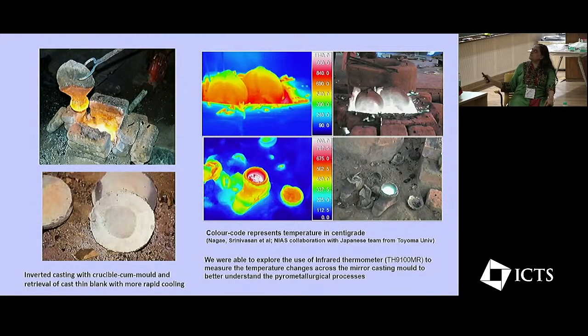We also use various other techniques. This is a thermal camera here, which is quite useful to understand what is happening in terms of the temperatures in the foundries. You can see the color coding here. What it tells you is that there's a huge difference in temperature between the top of this crucible cum mold, where the metal has been heated, and the bottom of the mold, where it has actually been cast. It's a very drastic drop in temperature of at least 300 to 400 degrees Celsius. I won't say it is totally like chill casting, but there is an analogy, it's almost like chill casting. So that results in a more homogeneous blank being cast.